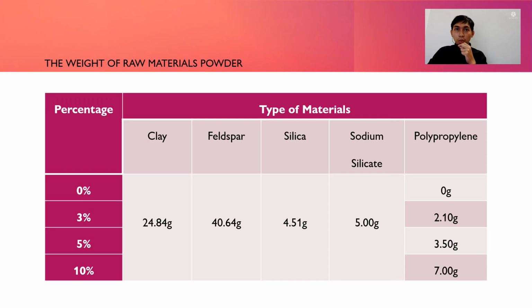Here is the table for the weight of raw materials powder. For clay, the weight is 24.84 grams, feldspar 40.64 grams, silica 4.51 grams, sodium silicate is at 5 grams, and for the polypropylene, at 0% is 0 grams, 3% is at 2.1 grams, 5% is at 3.5 grams, and for 10% is at 7 grams.